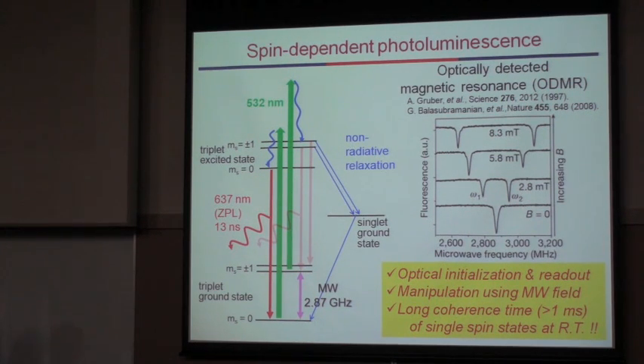And we can manipulate this spin triplet state by irradiating a microwave magnetic field, and this spin triplet state shows a very long coherence time, which is of the order of milliseconds, even at room temperature. This is a very big advantage, which is realized only in the NV center in diamond.